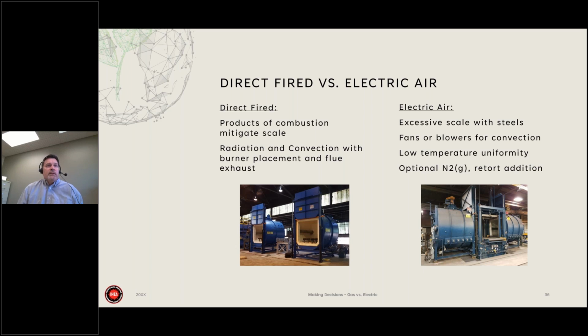Here's an example of direct fired versus electric air furnaces. These would probably be very common in heat treat and in process heat treatment. The direct fired uses product of combustion. It helps mitigate the amount of scale growth on steel parts. You can get radiation and convection with burner placement and flue exhaust, so you can get a good recirculation inside the furnace. The electric air furnaces would create more scale at higher and higher temperatures with the presence of oxygen. But you could, at this point, put in optional nitrogen gas or have it in a retort in order to keep the work in the process free of oxygen, although then that enters into its own scope 2 energy requirements for industrial gases.